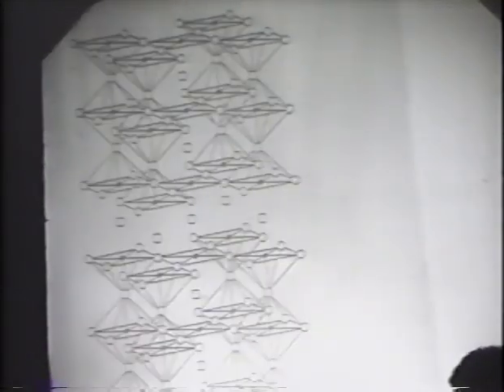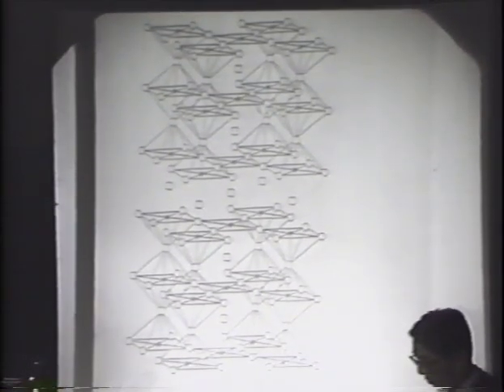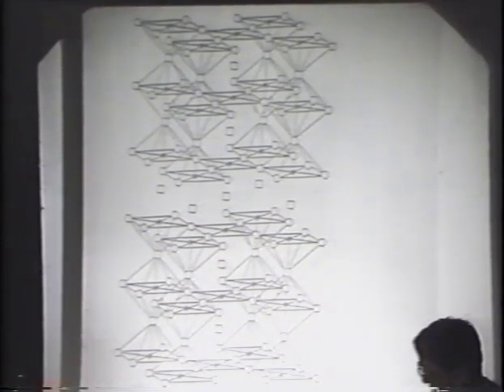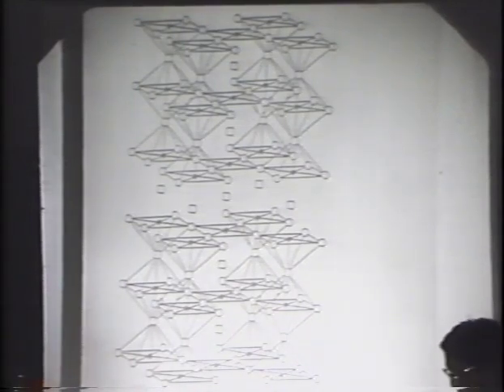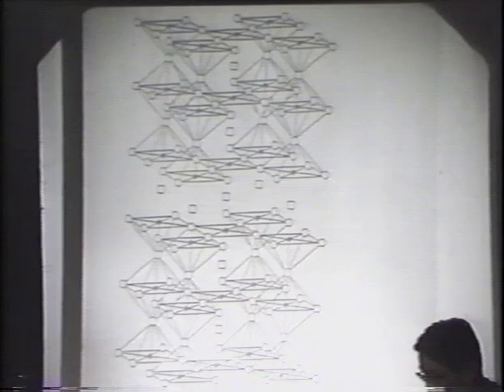Our crystal structure, the pattern of X-ray spectra, quite resembles that of lanthanum strontium copper oxide. First we thought that it is a perovskite type, but later we found a line of a triple layer period of C. Now we think that the crystal structure consists of triple layers. A model of this type of perovskite oxide was proposed by a French chemist group, as shown in this graph. But the position of the oxygen ions cannot be determined by the X-ray diffraction method. The correct identification of the superconducting phase is a future problem.